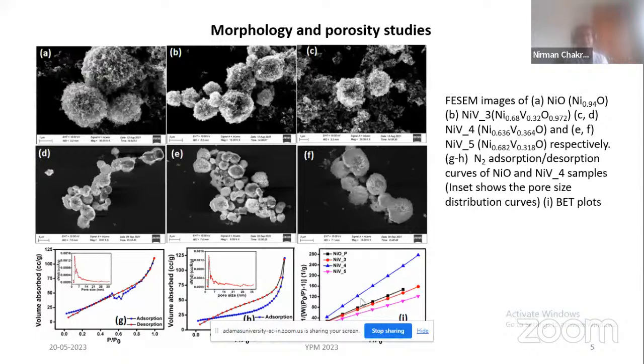Because in that case, we can actually compare the effect of the surface electronic structure and the bulk magnetism, so other factors are kept similar. We had a very planned way of getting this nanocluster architecture so as to have a greater surface area, so that they can interact more with the incoming gases. And we have a high BET surface area of about 70 meter square per gram.